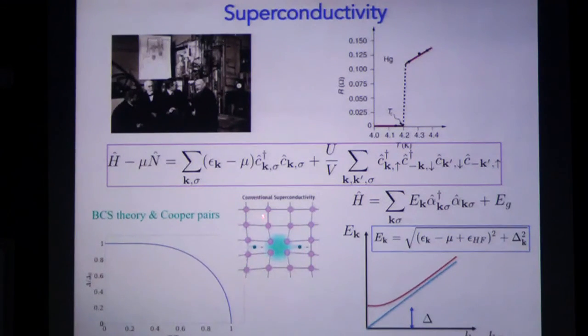And what we see here is the gap. It's the energy gap. The order parameter as a function of the temperature. Remember, as I told you, that the order parameter is a quantity that below the transition temperature becomes different from 0 and becomes 0 above the transition temperature. And what is important to say is that providing to the system an energy above this energy gap destroys the superconducting state.